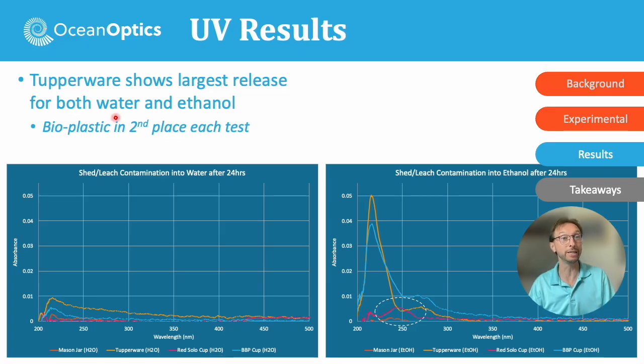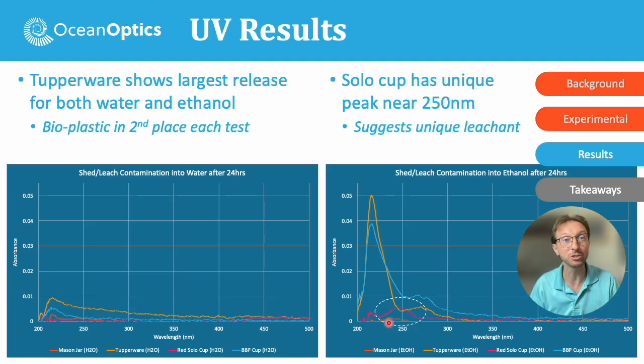So the Tupperware in each of these cases was the largest source of leachants in both the water and the ethanol, and the bioplastic was second place in each of those cases. But note the red Solo cup has a unique peak right around 250, just shy of that, like 245 or so, where these are back here more in the 220 range. This is suggesting there's a unique leachant from the red Solo cup that is different than what we're seeing coming out of the Tupperware or the bioplastic.